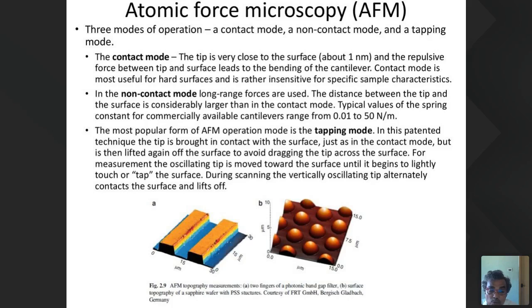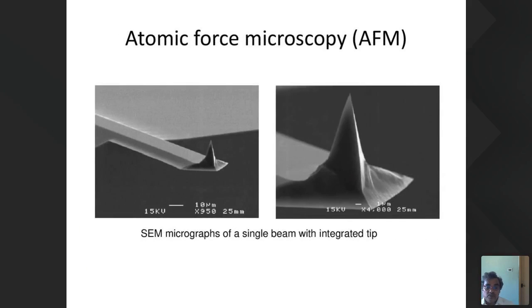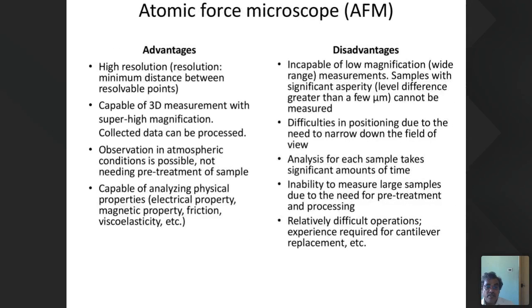For measurement, the oscillating tip is moved over the surface until it begins to lightly touch or tap the surface. That's why it's called tapping mode. During scanning, the vertically oscillating tip alternately contacts the surface and lifts off. These are some of the measurements taken. This is called a sapphire wafer. You can see the structure. This is the tip, a very sharp tip. Some methods use a single beam with an integrated tip. This is the integrated tip.